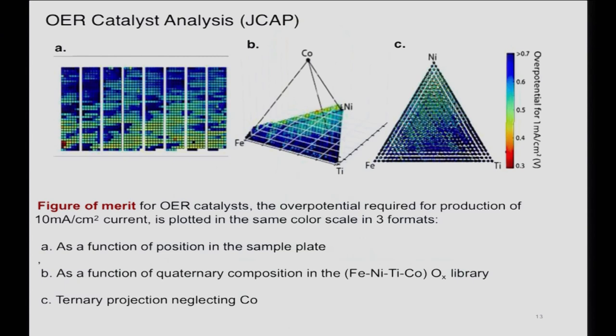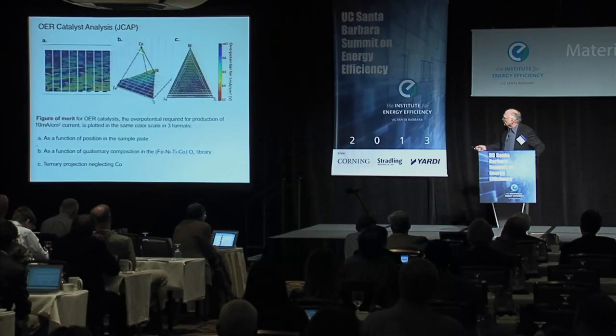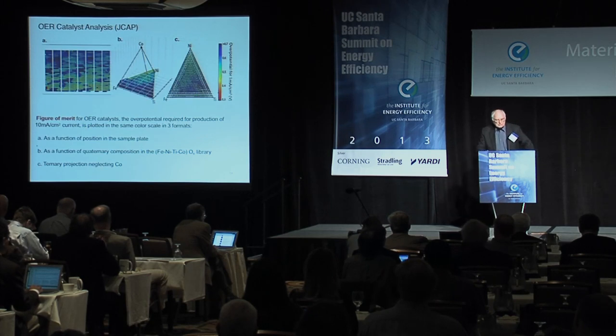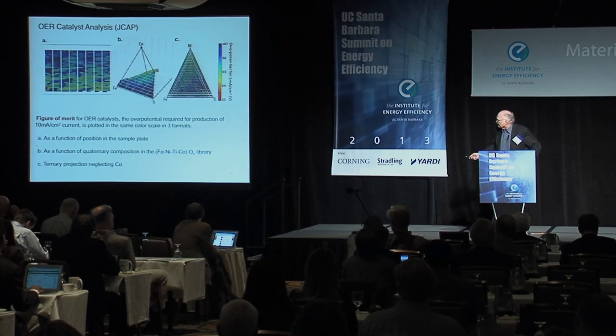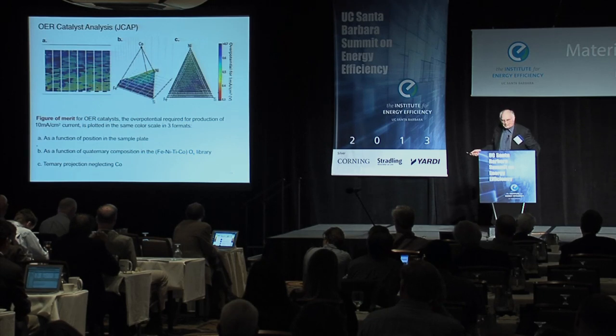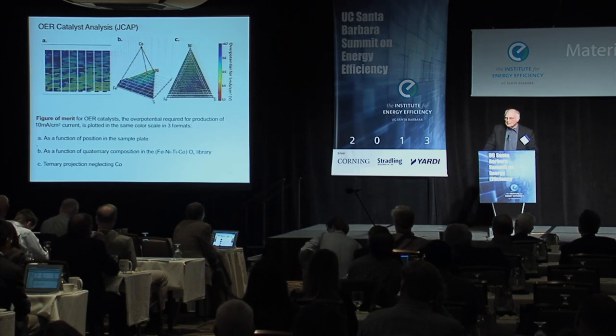But the point is that you can then look for systems and look for overpotential problems, and this shows the plotting of that and mapping out the figure of merit for some OER catalysts. On the left side, you can look at it as a function of the position on the plate, and the right side is looking at it in context of the phase diagram for the 4 components, and then you can take slices to it as well. The blue is not good, that has the high overpotential. The yellow, green is better, and the red is the best, but as you can see, they're few and far between, but they still exist there. And there are quite many variables in here, which have to do with annealing.